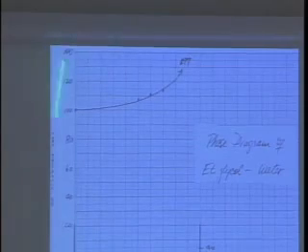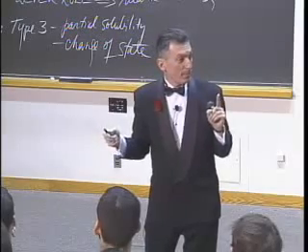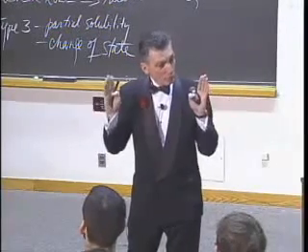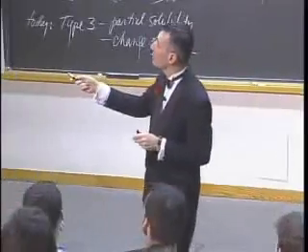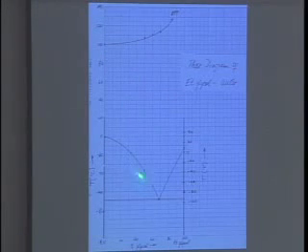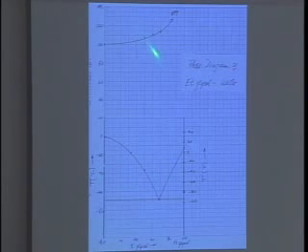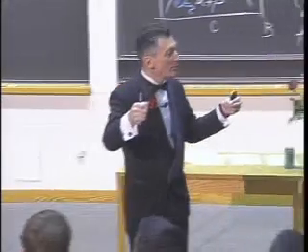So what we've done is we've taken this interval of liquid water, which at purity is 100 degrees Celsius. I haven't put the pressure cap on. If I just use 1 atmosphere pressure, water freezes at 0 Celsius and boils at 100 Celsius. If I add 50% glycol, it freezes at minus 35 Celsius and boils at about 106 degrees Celsius. So now I've widened the liquid regime.